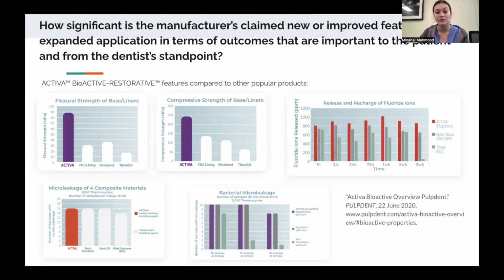Secondly, Activa Bioactive Restorative has statistically greater fluoride release after recharge at 24 hours, 1 week, and 3 weeks compared to the other groups tested. This is beneficial for the patients because it prevents demineralization of the teeth. Another study showed that Activa Bioactive Restorative, when tested in vitro for microleakage without a bonding agent, compares favorably with leading composites tested with the bonding agent. This saves money and time as the dentist doesn't have to perform the extra step of applying a bonding agent